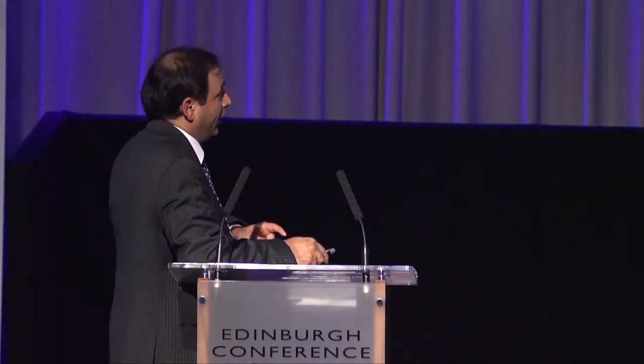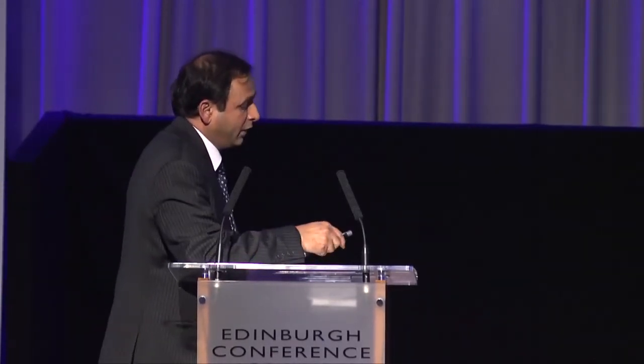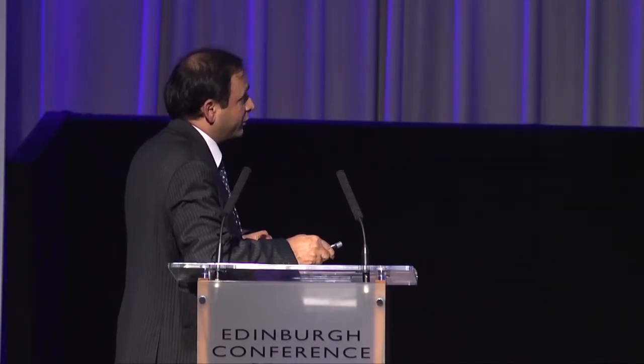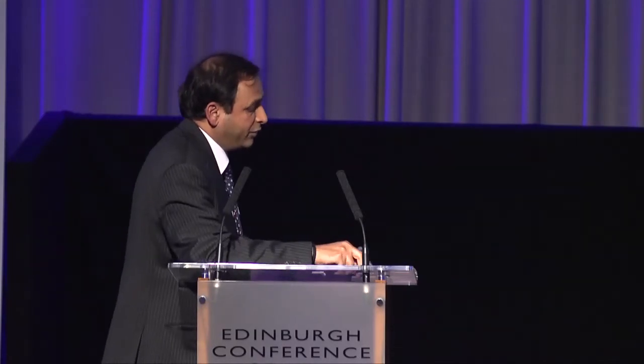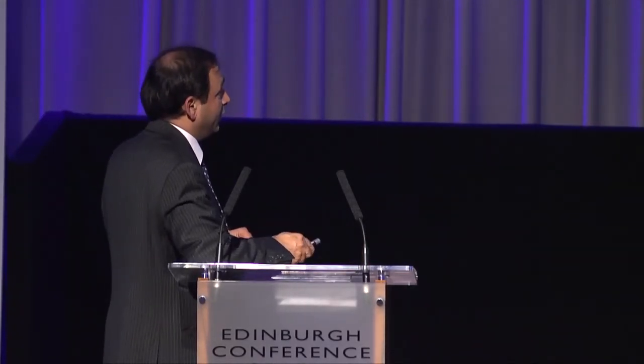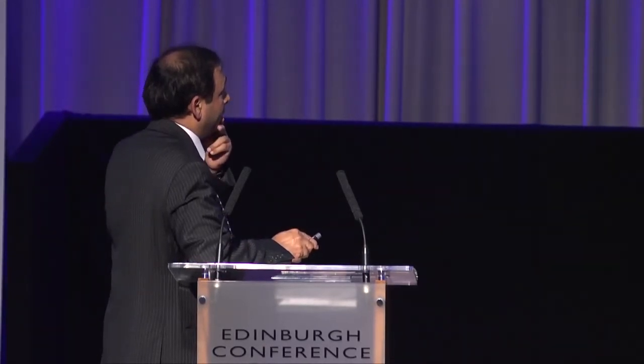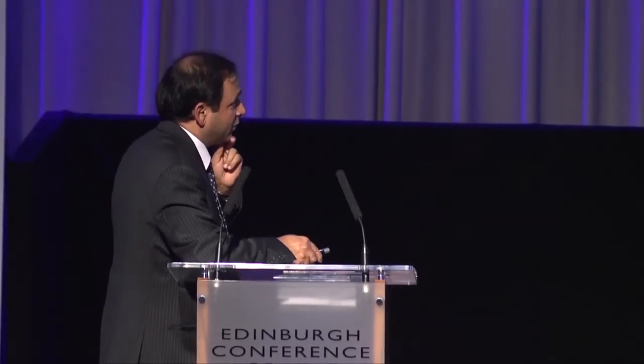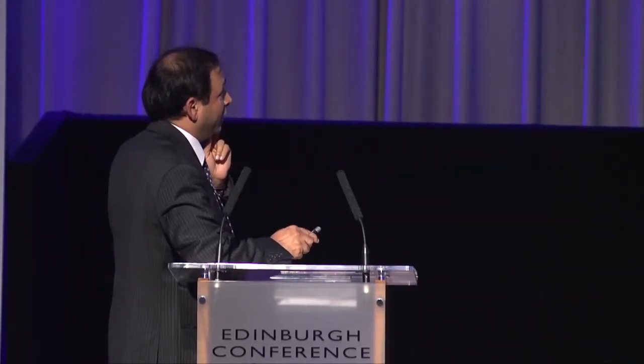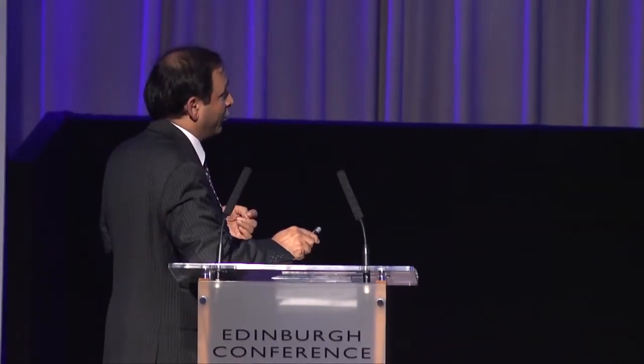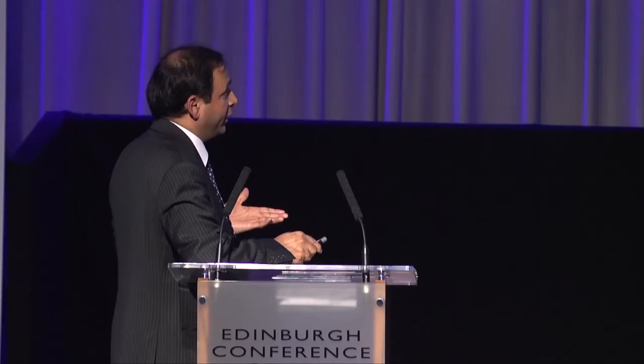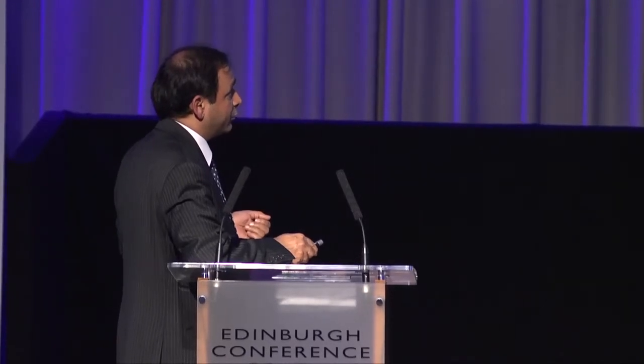which is quite significant. Based on this, and the CVD process that Glyndŵr University is using, we have achieved some very recent results, up to 5%, for about a 400 nanometer cadmium telluride layer and a CdS layer of about 60 nanometers. And we know that there are certain limitations of fill factor, which is not an inherent property of the device. These are coming from the contact ends, where there might be more shunt losses happening. So there is lots of scope where we can still improve upon this, work is going on, and we're hoping we will have some better results to follow.